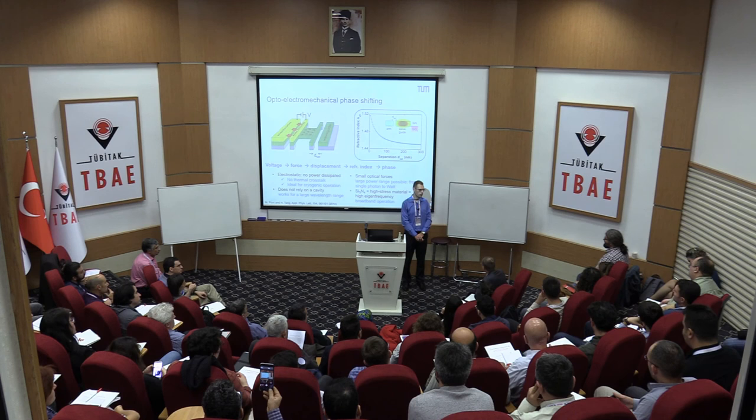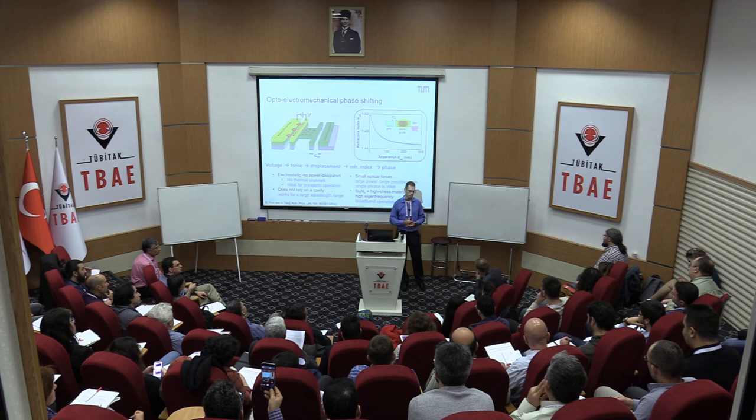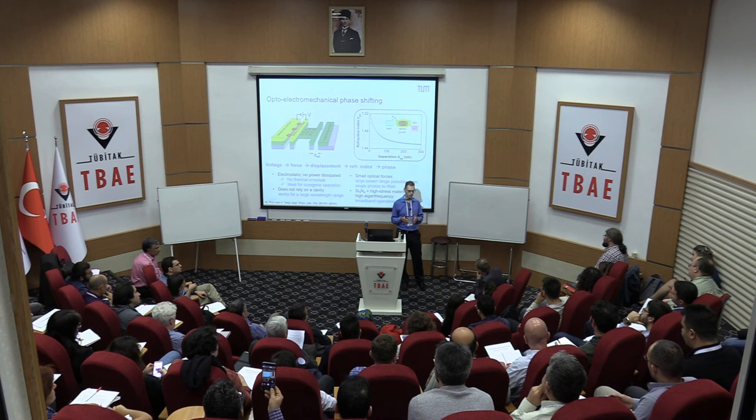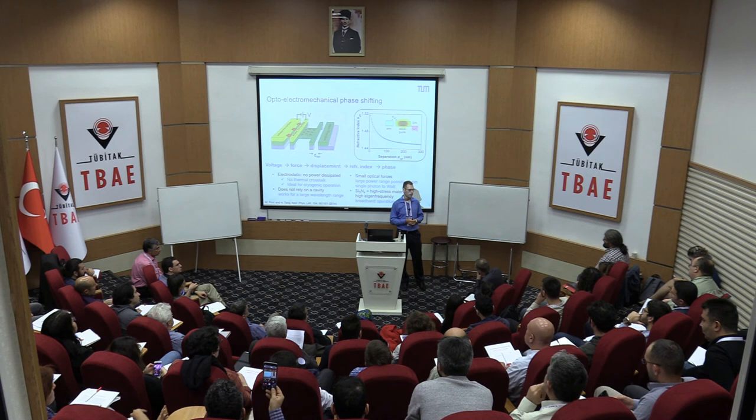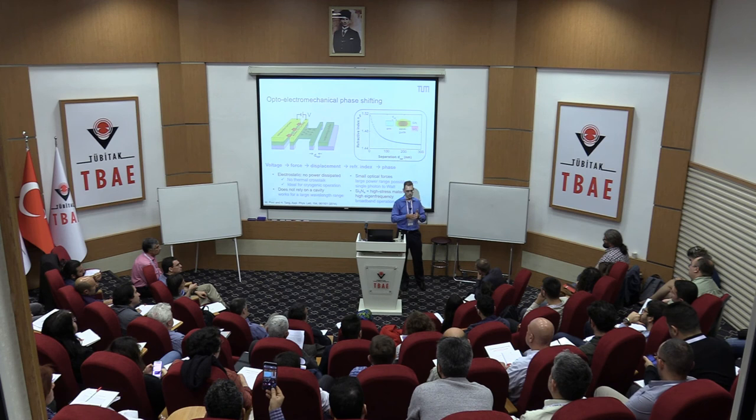So also from a more fundamental physics point of view, these detectors are still very interesting. People are still trying to figure out what the exact mechanism is, how the Cooper pairs are broken, then being transferred to the lattice to break other Cooper pairs and so on. Because it is a single photon, it has an energy of about an electron volt. These Cooper pairs have much less energy, and still you need to break the superconductivity in this entire wire to get a big voltage pulse.